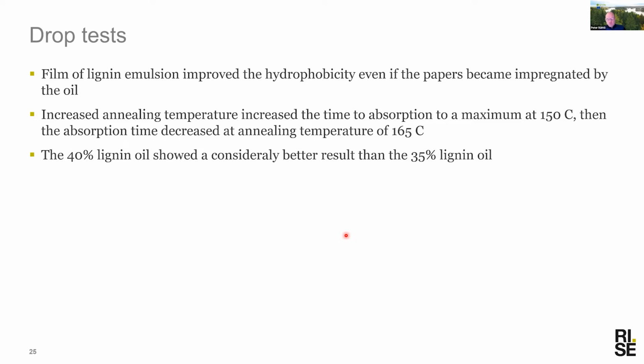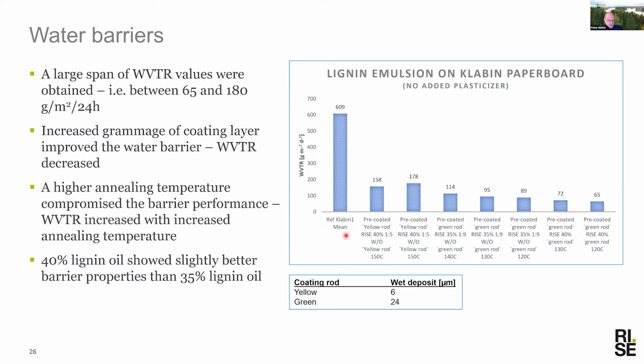We had pretty promising results when it came to the drop test. We have a surface that is kind of closed. When we measured the water vapor transmission rate, we got quite promising results. If we look at the baseboard, we have quite a high value here. This is actually the pre-coated board. When we had an annealing temperature of 150 here, we had a little bit higher transmission rate than when we went down in temperature.